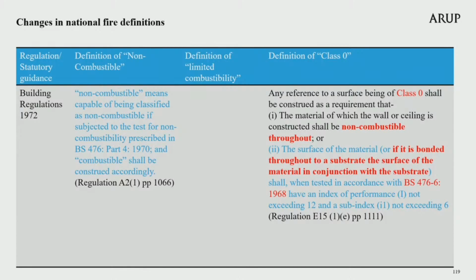Part 6, the fire propagation test, had been created by the BRE in 1968 after they had identified that the highest classification, Class 1, from the surface spread of flame test could not differentiate between different combustible linings. The definition of Class 0 reference was therefore changed to refer to Part 6 only. The combustible substrate with a non-combustible surface definition was dropped, leaving 2 options for the definition of Class 0 instead of 3. Again, constructed as non-combustible throughout was retained, and the second option, as shown on the screen now, relying on the Part 6 test.